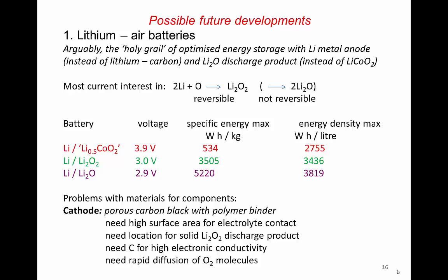So currently it's a hot topic in R&D in lithium battery materials. At present, there's most interest in a halfway reaction, which is lithium plus oxygen forming Li2O2, lithium peroxide, because this reaction is reversible. So we're not interested in just having a single primary battery. We want this to be reversible and rechargeable over many cycles. So the first stage, forming lithium peroxide, is reversible, but the second stage, forming Li2O, at least at present, is not reversible.